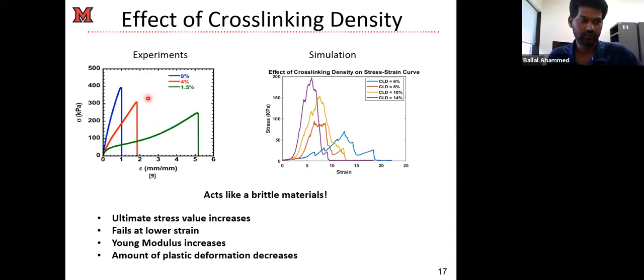They studied the effect of cross-linking density. They found that when they increase the cross-linking density, the material behaves like a brittle material. At low cross-linking density, it is kind of rubbery because you don't have that kind of resistance; it just flows when you do a rheology test for the polymers, because there is not that much cross-linking. But when you increase the cross-linking density, it gives the material more rigidity, and it fails like a brittle material. The peak stress increases and the strain at which it fails decreases.